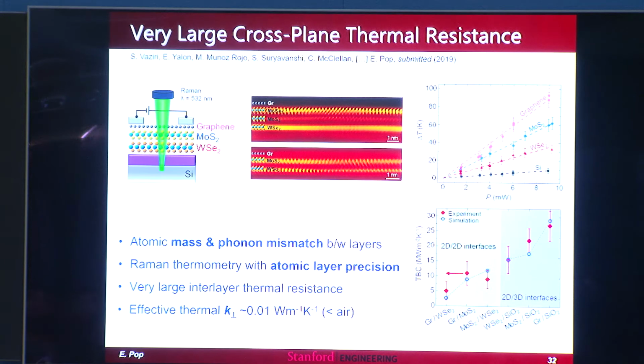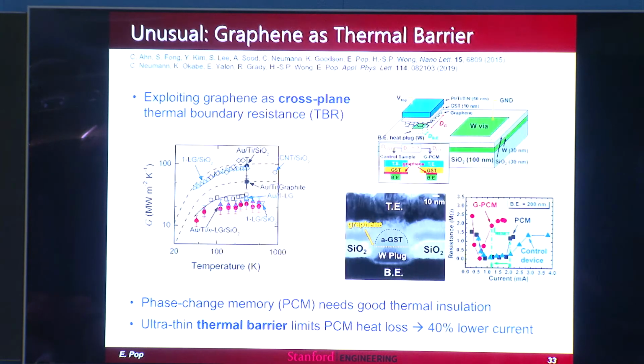And it's just relying on simple acoustic propagation, or in this case, acoustic impedance mismatch concepts, where we're just deliberately layering light and heavy atoms. You can actually see that the worst thermal conductance is between graphene and WSe2, and that's not a coincidence, because that's the biggest mass mismatch between the materials. Okay. There's actually an application for this, it turns out. Of course, you can block heat. That's great. Maybe it's something to wear in the cold winters.